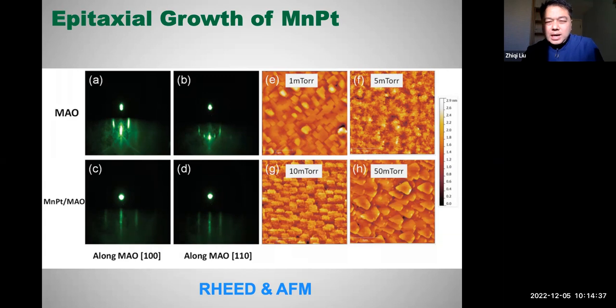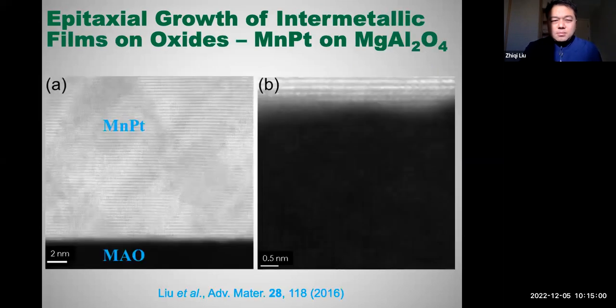And we can always try to optimize the growth conditions of the sputtering. For example, the argon pressure and the growth temperature and also the post-annealing temperature. You can try to make the growth slower and slower, try to simulate the growth conditions of the molecular beam epitaxy, and that makes the epitaxy easier. After the growth by the sputtering, we can get high quality thin films of magnetic metals.